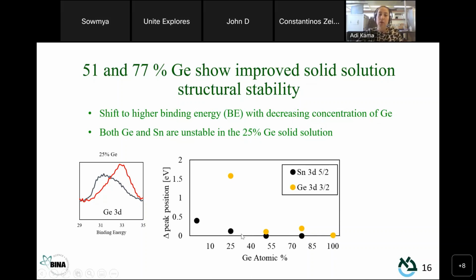We see that for high concentration of germanium, we have almost no shift in binding energy position, indicating no oxidation. And when we move to high concentration of tin, we see oxidation of both tin and germanium to higher oxidation states. Again, it's indicating degradation of the materials that will eventually degrade the solar cell.